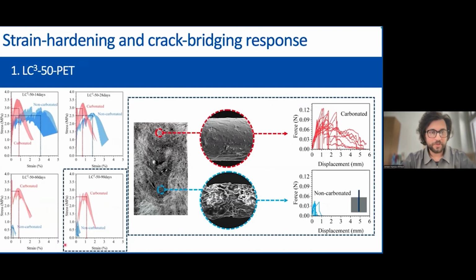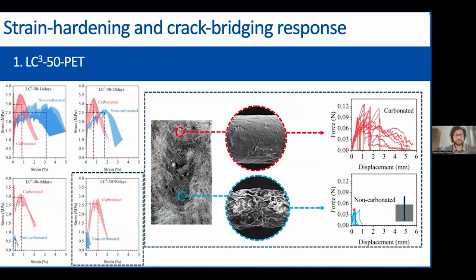And to go further into why this happens, I will show you the results of this 90-day specimen. We looked at the fracture surface and saw that you can see PET fibers in the area where the CO2 could penetrate and reduce the alkalinity, but in the core where CO2 couldn't reach, the fibers were almost invisible, at least to the naked eye. Also, we did the single fiber pull-out test, and the effect of carbonation in mitigating PET degradation becomes very prominent here. This is for the 90-day results. You can see for the carbonated, the fiber bridging or the bond between the fiber and matrix was preserved almost entirely, while the non-carbonated samples lost their fiber-matrix interaction.